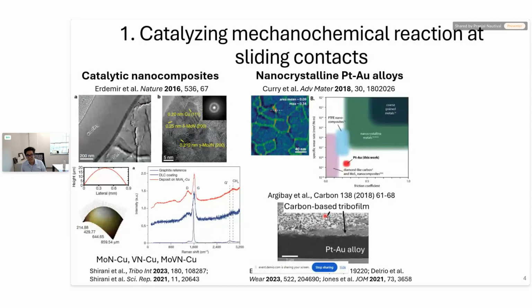And they have discovered the structure of these films and the nature of these reactions can be controlled by changing the composition of platinum gold alloys, as well as the conditions play an important role in the final composition. I should mention that these experiments did not rely on oil molecules to form tribofilms, but actually these were conducted most of the times in nitrogen environment. So inert gas or nitrogen gas, and the nitrogen gas contained some organic vapors. So it is those organic vapors that reacted on these catalytic surfaces to form carbon-based tribofilm.